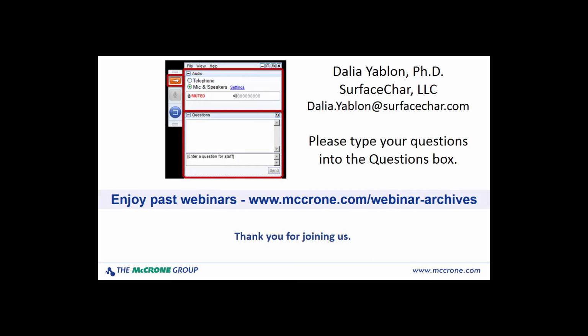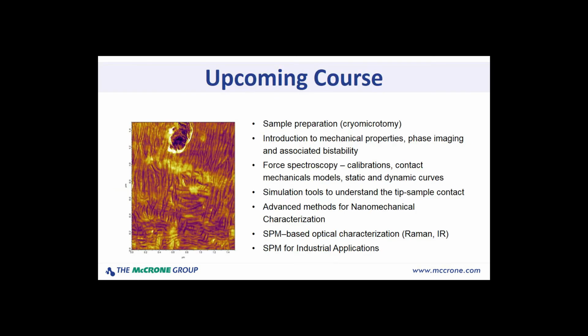So in air, AFM now, research level instruments under certain conditions and with maybe more sophisticated modes can get atomic scale resolution. And I would say that's really been around probably the past 5 to 8 years. It will be sample dependent. If you can immerse your sample in a liquid, that's something that really helps get at that higher resolution. So I don't push the atomic scale resolution because it's not something that's really applicable to any sample that you throw in under your system. It'll also need to be well prepared.